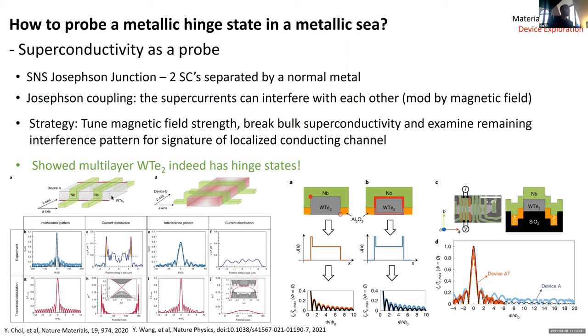And we did experiments where we put the electrodes this way versus where we put the electrodes, it's hard for me to draw, but you know, this way. Or actually it's drawn here, along the B axis versus along the A axis. And sure enough, we did see that. The point is, orthogonal to the hinge states, we do see a huge difference in the Fraunhofer pattern, and we don't see the same SQUID coupling as expected, because these supposed hinge states in this direction should be lost by mixing into the bulk.